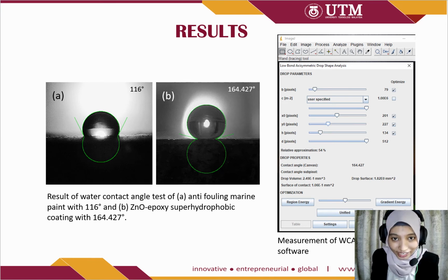So to characterize the sample, a contact angle test was made using the sessile drop method. As you can see in the photo, the result of the water contact angle test: on the left side is anti-fouling marine paint, which is 116 degrees, and on the right side is the zinc oxide superhydrophobic coating with 164.427 degrees, where a superhydrophobic characteristic must be more than 150 degrees. It was measured using ImageJ software.